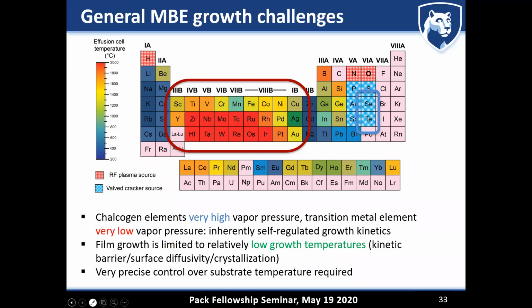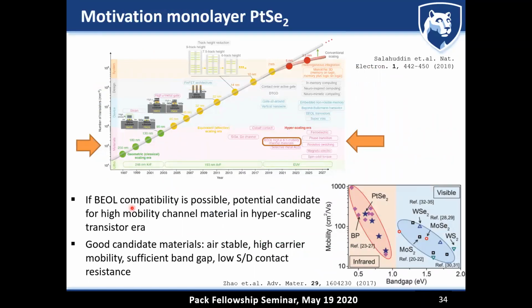But this is interesting because if you look into what people are doing right now to replace conventional semiconductors, and you're looking at the trajectory of low power logic devices, focusing on the material here, you can see that in this current area, called the hyperscaling area, BEOL, high electron and hole mobility channel materials are interesting. BEOL stands for back end of line. So if you can grow high quality semiconducting materials with thermal budgets below 450 degrees C, that becomes very interesting. And among those, people have worked a lot on tungsten diselenide and molybdenum diselenide, but they don't have the greatest mobilities. Among them, platinum diselenide is very interesting because it pushes the envelope of mobility to orders of magnitude that are typical for silicon as well.